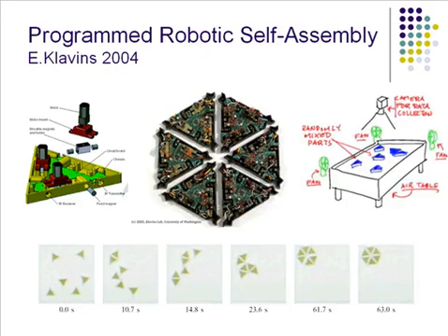But here we actually have more freedom to design this process to achieve better yield. So, for instance, if you allow only dimers and inhibit the formation of trimers, then all the species become dimers first. Then those can be connected to make a hexamer. This kind of grammar improves the yield a lot. And also, you can design various kinds of self-assembly on the processor.